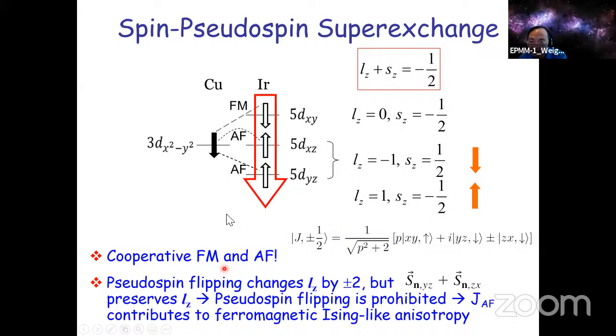Then how about the spin excitation gap? That's coming from the anisotropy, because when you try to flip a pseudo spin, actually you change the LZ, the orbital magnetic moment along the z direction, by plus or minus 2. But in the real spin interaction, this operator actually preserves LZ. So that means the pseudo spin flipping is prohibited. When the flipping process is prohibited, it will generate a ferromagnetic Ising-like anisotropy. But this ferromagnetic Ising-like anisotropy comes from the original antiferromagnetic superexchange.